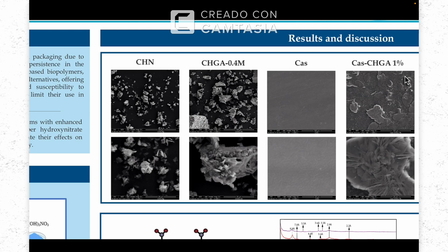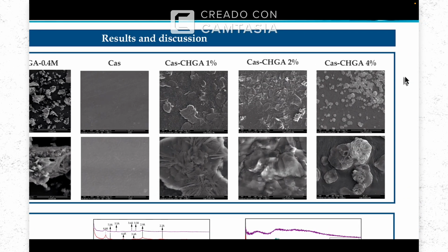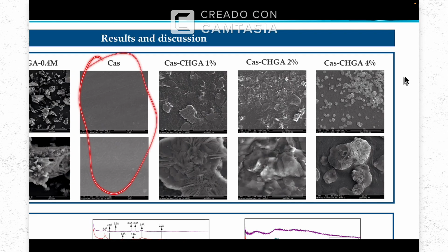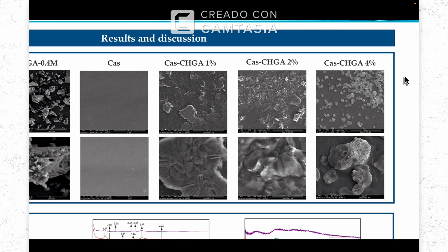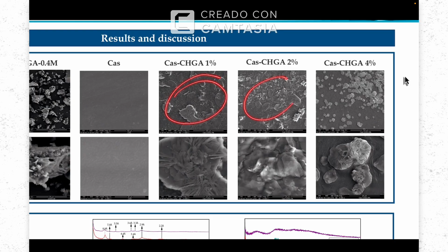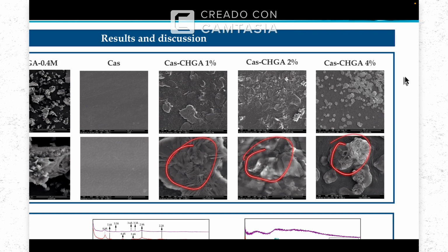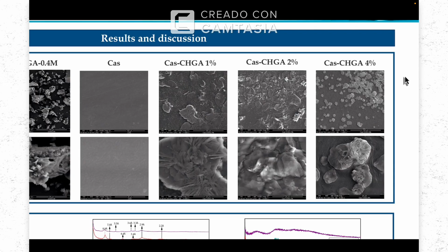Now, when we observe the film morphology, in the original calcium caseinate films we observe a very smooth surface, but after the incorporation of the copper hydroxynitrate functionalized with gallic acid, we can see some texture in the surface that corresponds to the copper hydroxynitrate material that is not fully incorporated in the film.